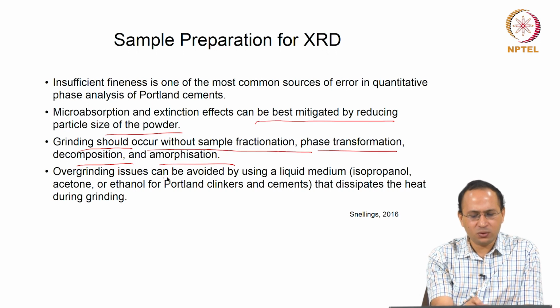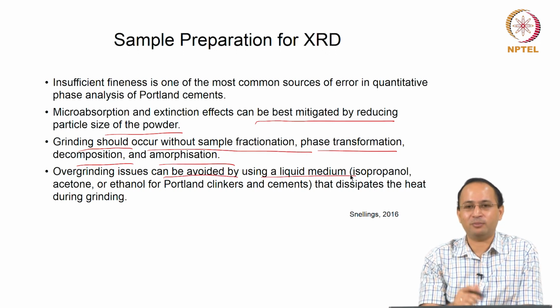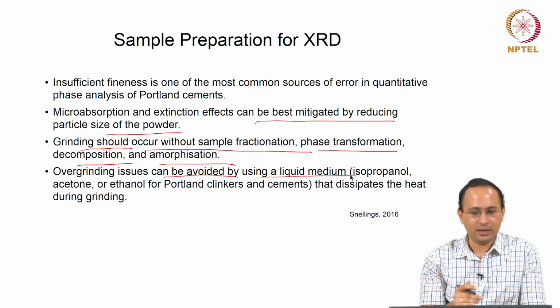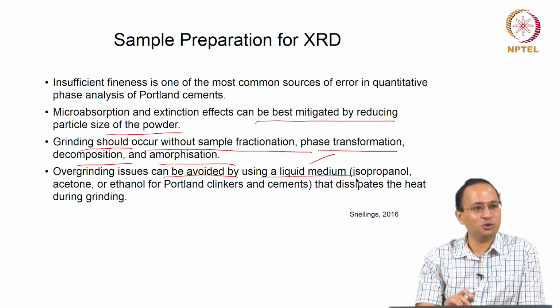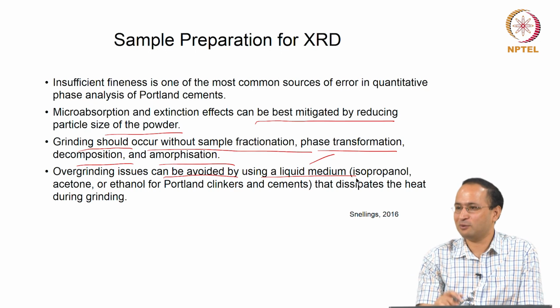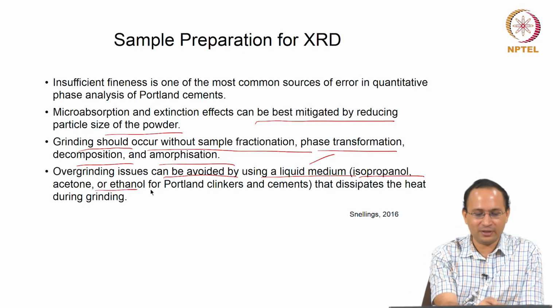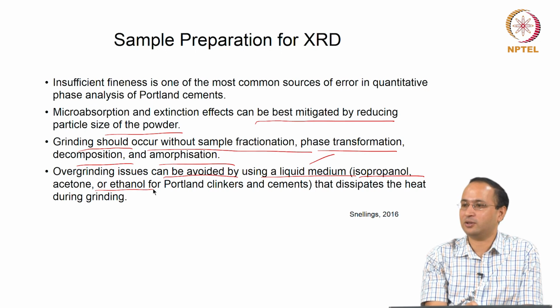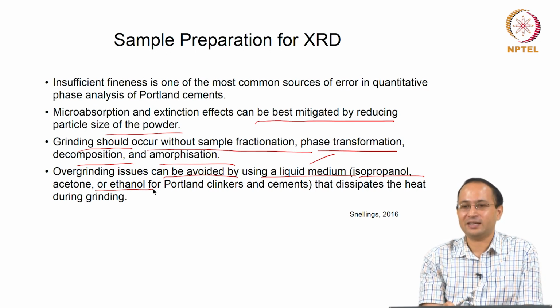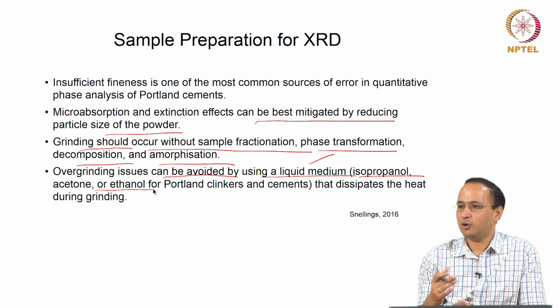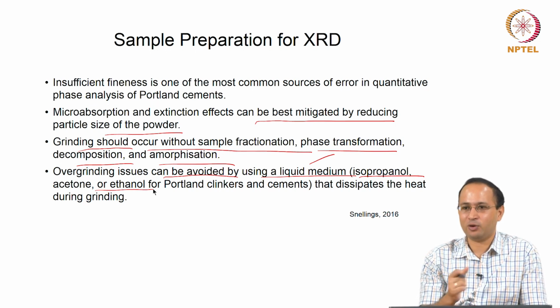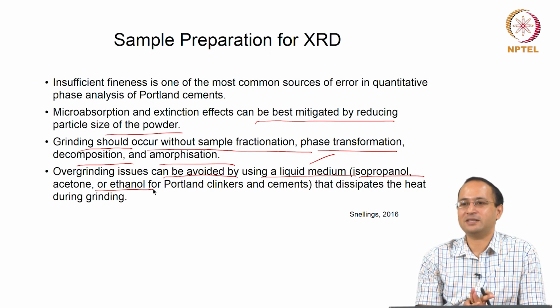Over-grinding issues can be avoided by using a liquid medium. Now, how do you resolve it? You can use a liquid medium while grinding, so that will dissipate the heat. But we can't use water, because water will again react with the cement. So, we can use isopropanol, acetone, or ethanol; these are commonly used for Portland clinkers and cements. That way you make sure there is no further hydration, and at the same time heat is dissipated, so the phases are unaffected.